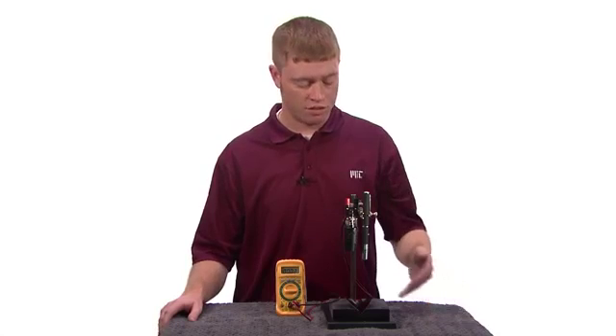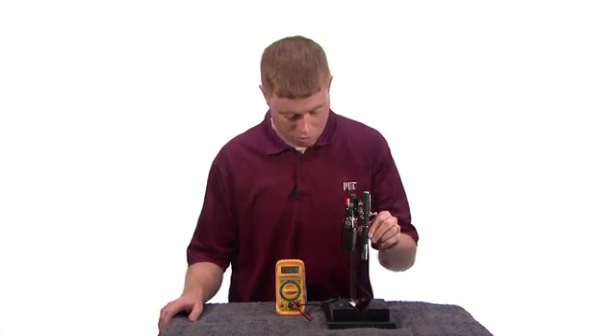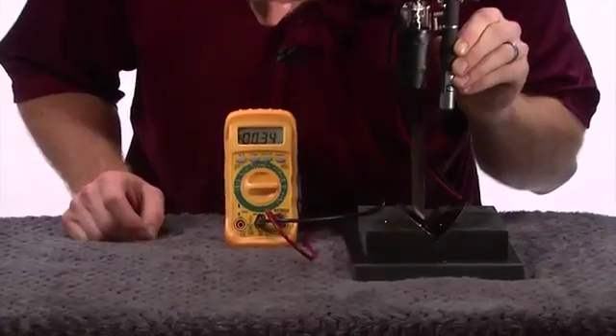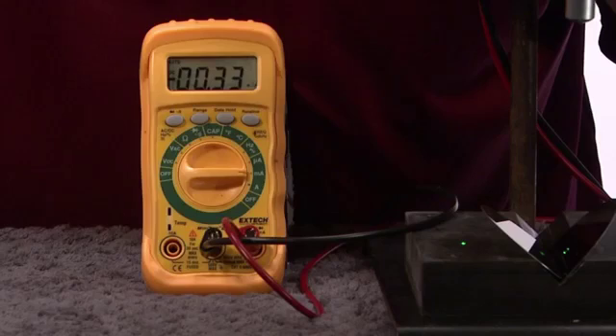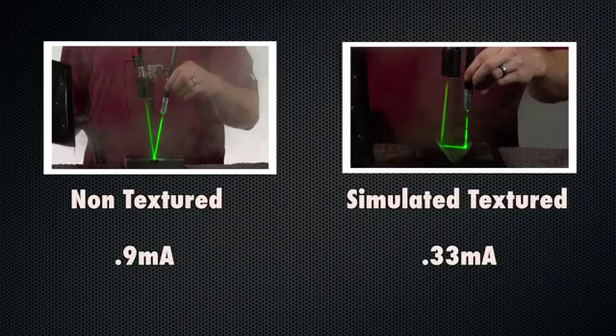Now that the steam has settled, we can get an accurate reading of the reflectivity of our modeled silicon surface. When I turn on our laser pointer, so now we can see that our photodiode is reading around 0.33 milliamps. This corresponds to around a 9% reflectivity, which is quite a huge reduction from what we had before, by about a factor of 3.